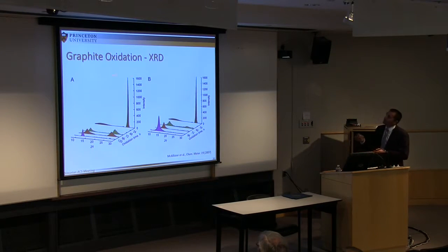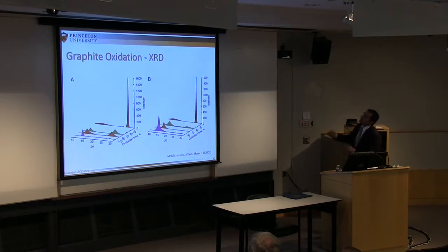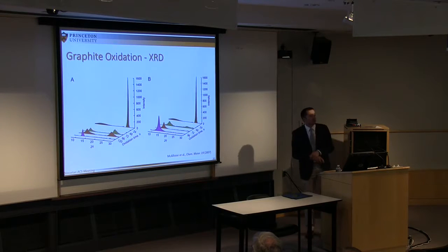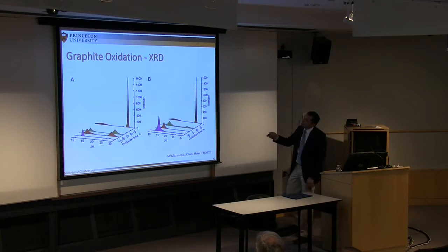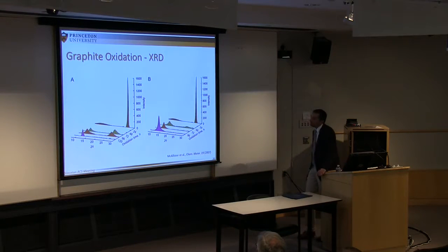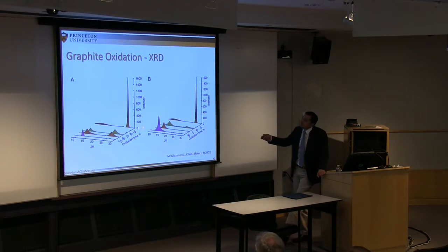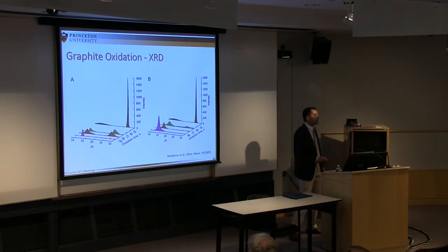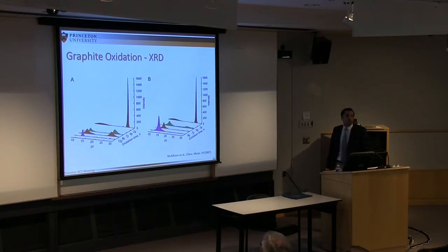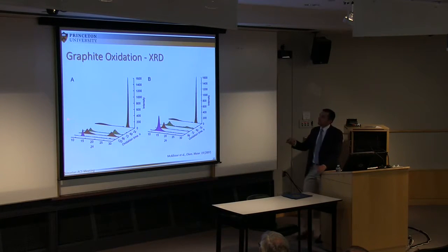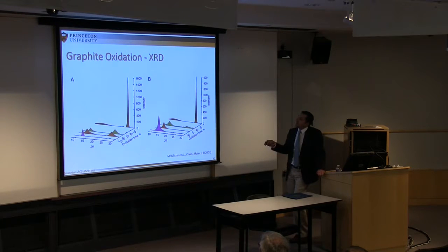On the left is an XRD study, again with the goal of showing that we have indeed successfully obtained graphene. We're starting with graphite flakes of 400 or 500 micron in lateral size. At the beginning, before the oxidation starts, you have the native graphite peak at 0.34 nanometer. That is the signature of the lamellar structures. As the oxidation process starts, you see that the fingerprint of graphite goes down, and you have another peak appearing here. This corresponds to a separation of about 0.7 nanometer now. That is the indication that you are now exfoliating your graphite. However, you see that you still need to go to quite high time durations.